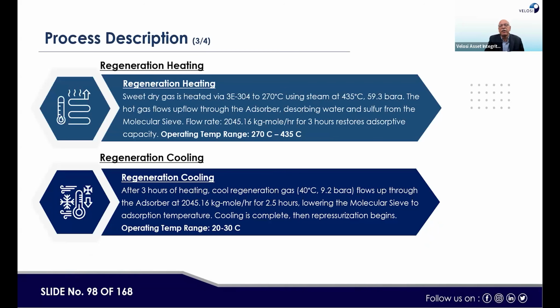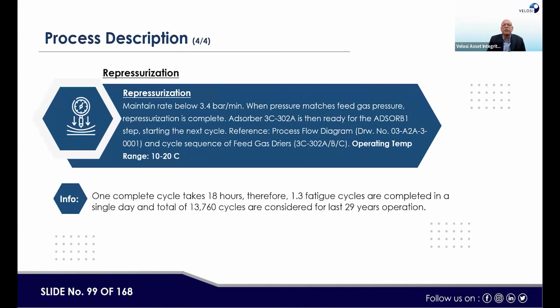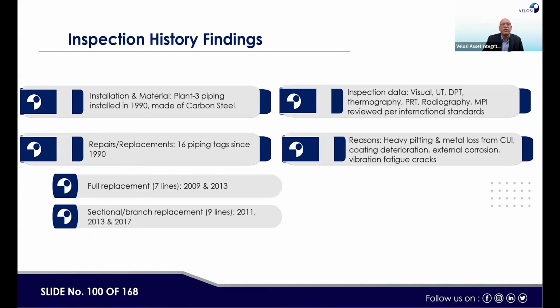Then in the regeneration, high temperature gases are passed through the bed to activate it, at 270 to 435 degrees Celsius. And then regeneration cooling is done to 20 to 30. So it means that there is a lot of variation of temperature, which is causing a lot of thermal expansion and contraction in the piping system, which causes these cyclic loads on the piping systems. Then repressurization means the system goes again to operation. So here, one complete cycle is not 12 hours, it is 18 hours. Therefore, 1.3 fatigue cycles are completed in a single day, and a total of 13,760 cycles are considered for the last 29 years of operations.